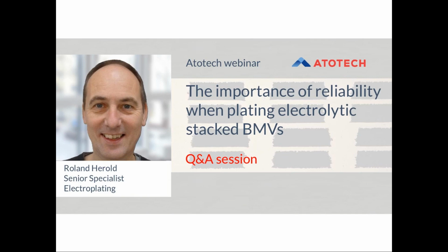If you have the TOC increased by any foreign chemicals, as mentioned before, for example, you have strong nitrate contamination in the copper oxide powder, what is a common problem. If you have, for example, other organics in the sulfuric acid, which is not very clean, and so on, these organic chemicals also containing nitrogen, also containing sometimes chloride or sulfur. And if you drag in such elements or they leach out from dry film, for example, the dye of the dry film, all these elements contributing then to the adsorption of chemicals on interfaces. And here we see a strong impact.